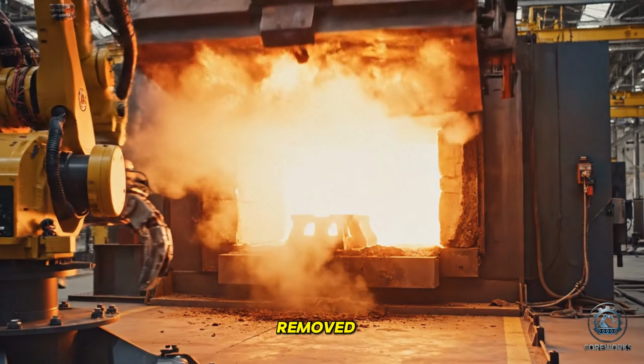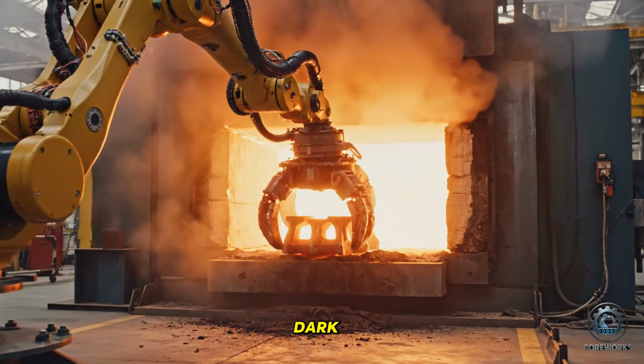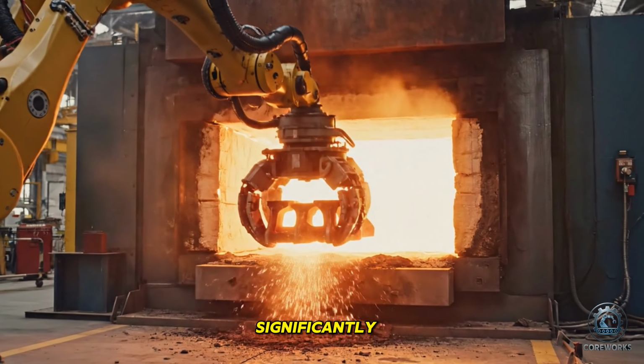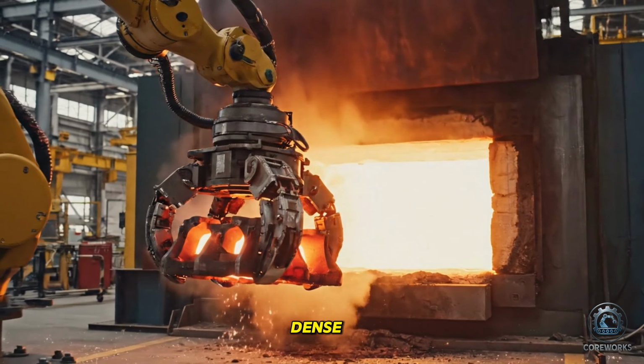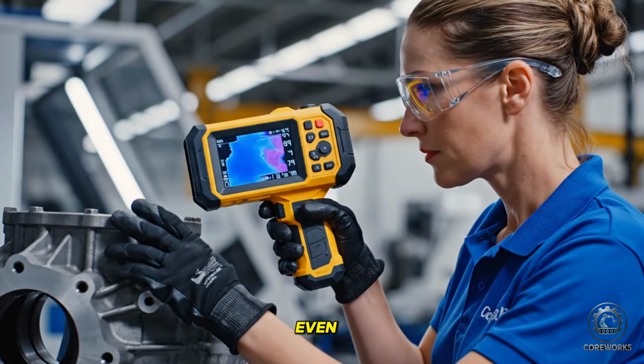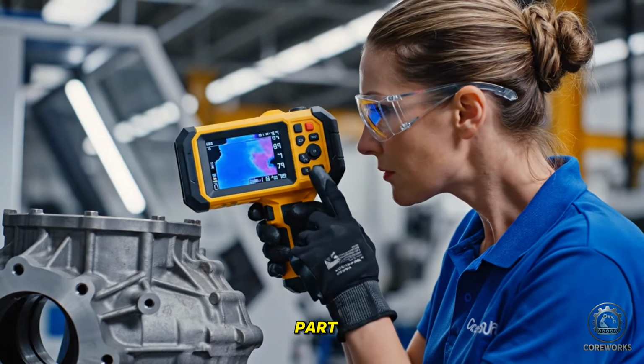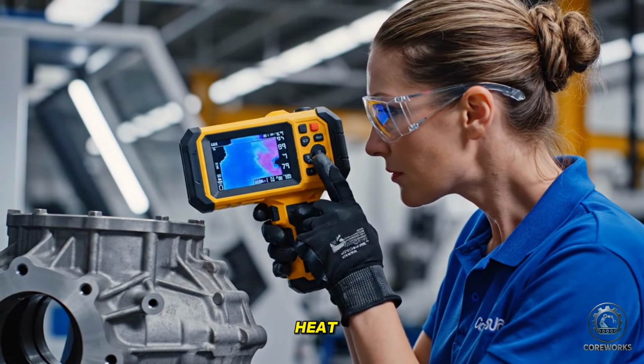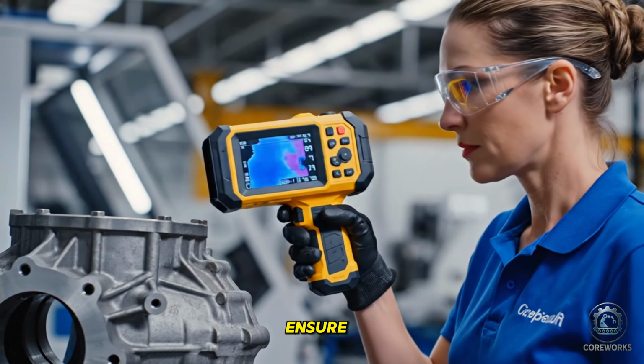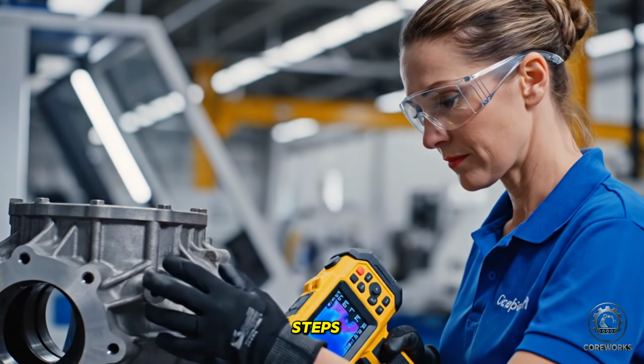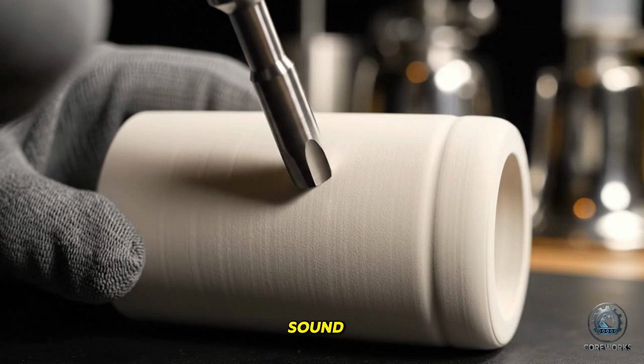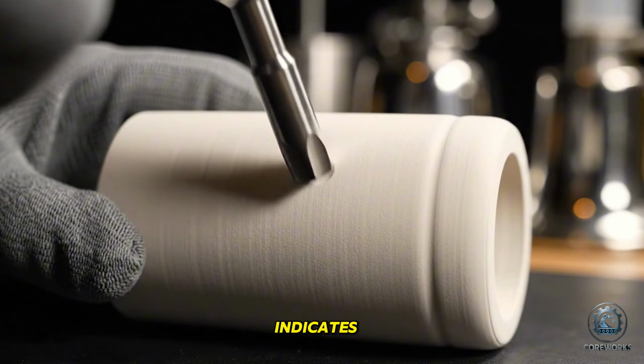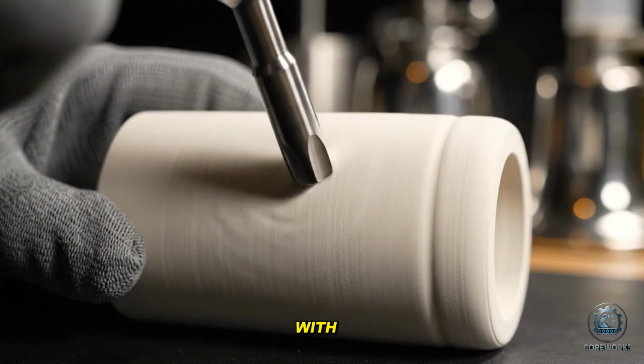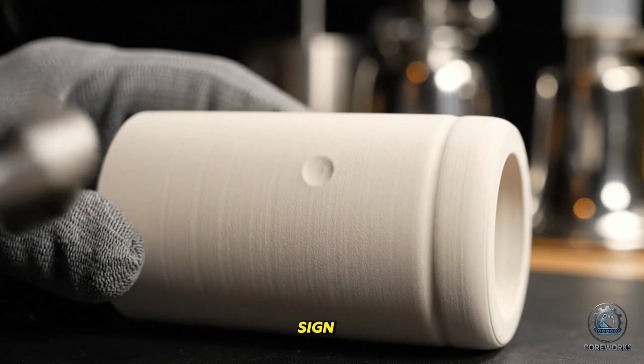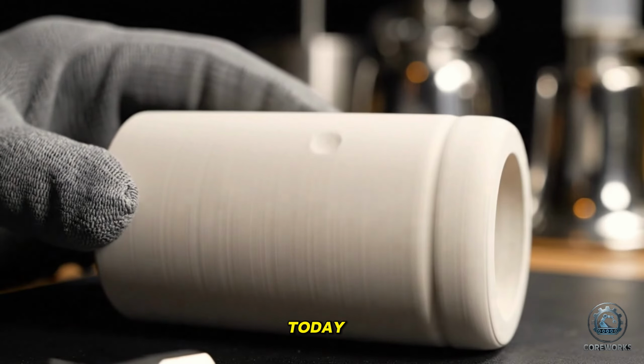The foil is removed. It has changed color to a dark, matte gray and has become significantly smaller and much more dense than before. Even after hours of cooling, the part still retains significant heat. We use thermal imaging to ensure it is safe to handle for the next steps. Listen to that sound. The high-pitched ring indicates a perfect, dense structure with no internal cracks, a sign of a successful sintering process today. The material must now rest.